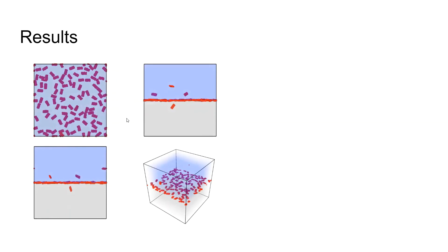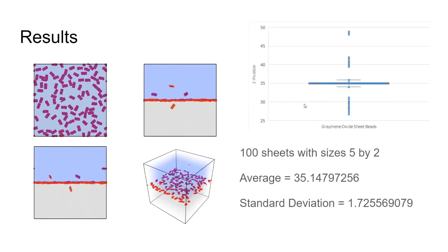Here is an example of a similar solution, but in this case the sheets are 5x2 instead. As you can see from the overview, there are a lot more sheets involved, and from the zx and zy views, there are actually beads that are not directly at the interface — some are floating in both the blue and gray solutions. Most of the sheets are still at the interface around z=35, but from the z position, some sheets are both below and above. One sheet is around z=30, and there appear to be two sheets — one near z=50 and one near z=40 — though the z=40 ones are actually two overlapping sheets.